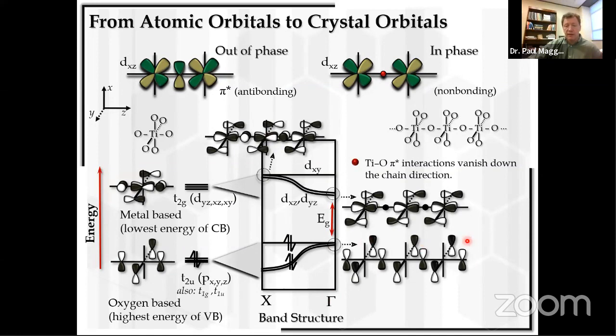Whereas the oxygen levels, they remain fairly constant at the top. And so that highest occupied orbital within your electronic structure in the valence band is always predominated by non-bonding oxygen orbitals. And so it's very hard to move this up and down in energy to lower the band gap. It's very easy by changing transition metals to change the position of the conduction band here.